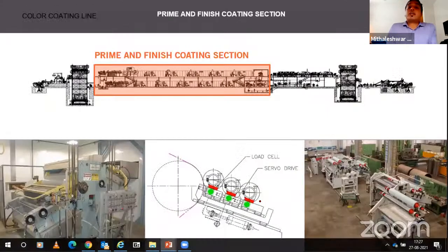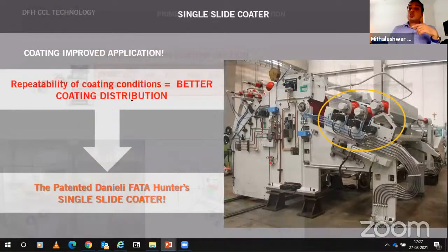I missed the slide, but okay, I can explain. The reason, if I draw the hysteresis in this case and also the stack design, the delta deviation of the forces in this coater design is only 6 pounds instead of 120 in the conventional stack design. 120 pounds of pressure deviation is not able to control the coating thickness up to 2 microns.